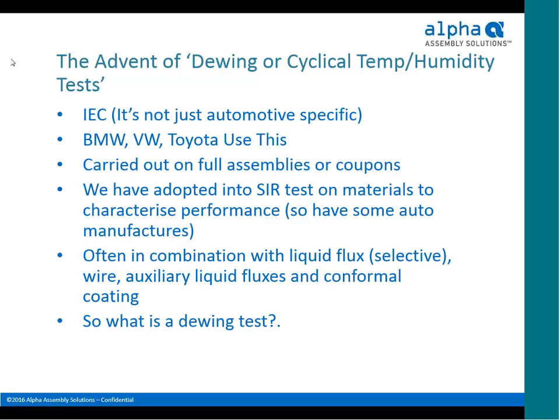We've adopted the SIR test that we run and these conditions to generate a customized hybrid cyclical test that reflects IPC J-standard SIR test protocols. In many cases, we'll run these tests in combination. These are really meant to generate test conditions that are typically seen by an assembly. So we'll build test coupons in an assembly style format. We'll use solder paste and then cover that with liquid flux and wave solder it, and then we'll hand solder. So we'll have multiple applications of flux. And then in some cases, there'll actually be conformal coating applied to the assembly or the test coupon to reflect the material stack up in the assembly.